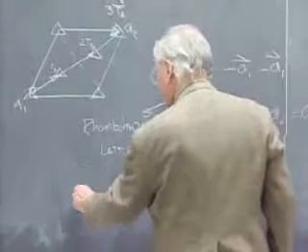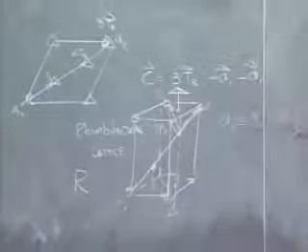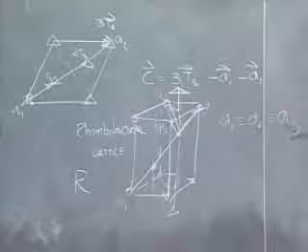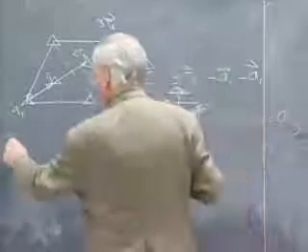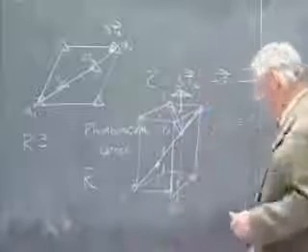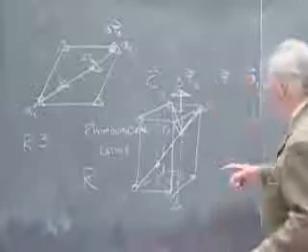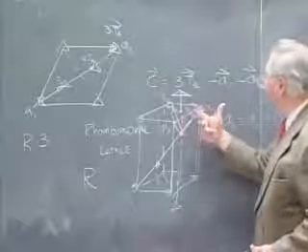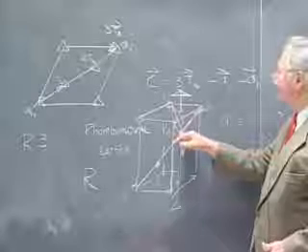And this is represented in a space group symbol by the letter R, standing for rhombohedral. So just the threefold axis with this choice of translations, that would be space group R3. A1 like this, A2 like this, A3, I'm taking a right-handed system, comes from the centered lattice point.